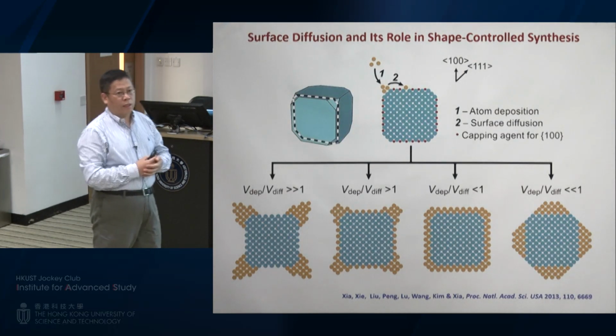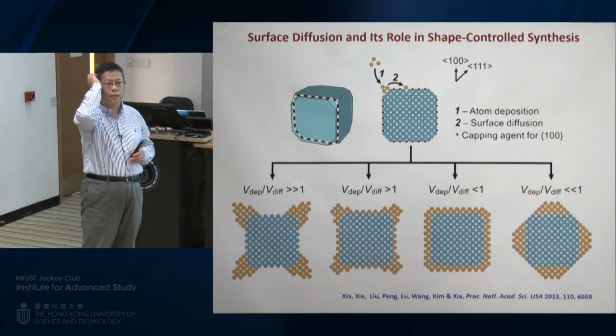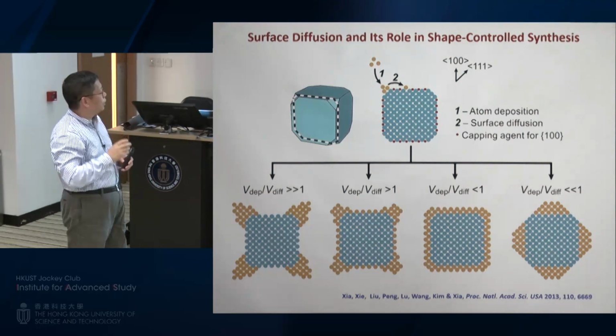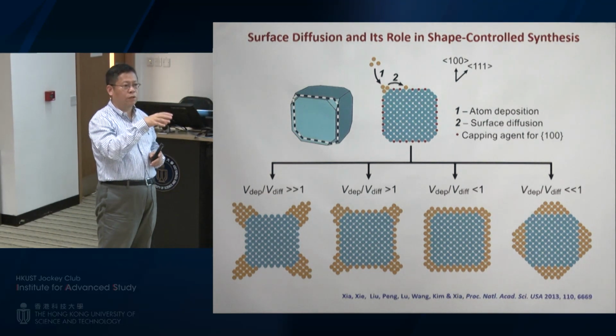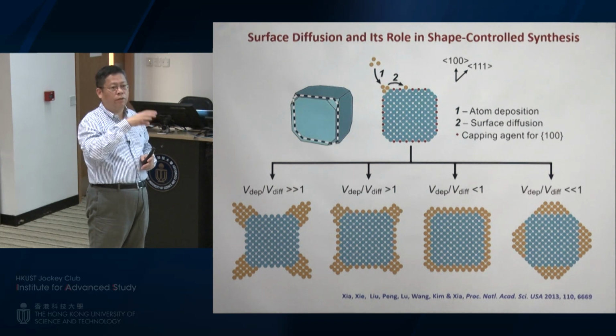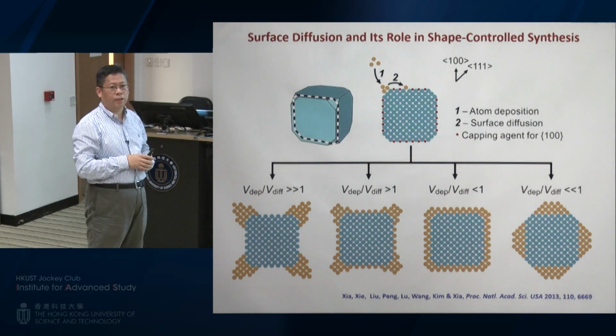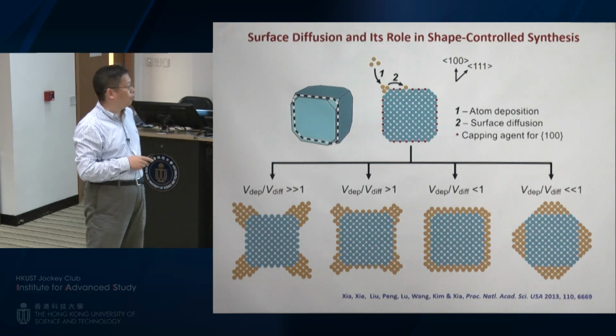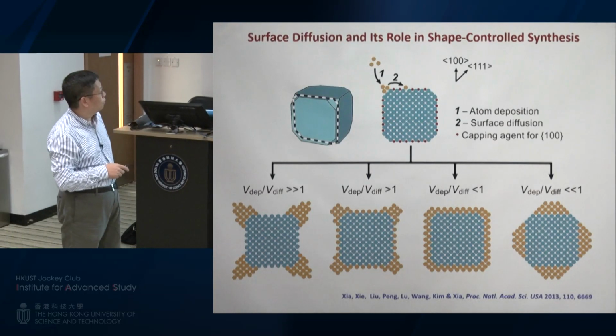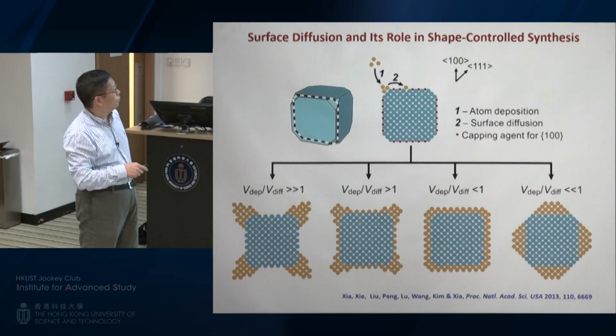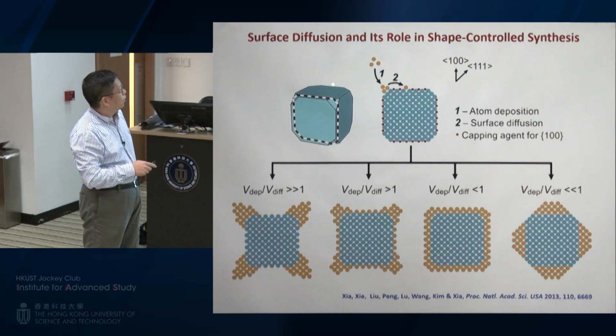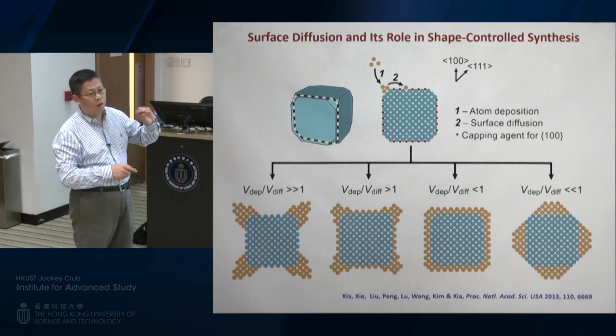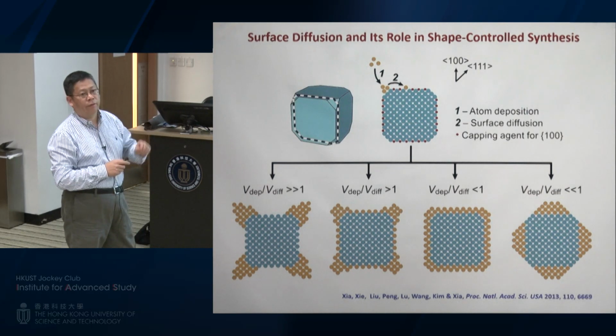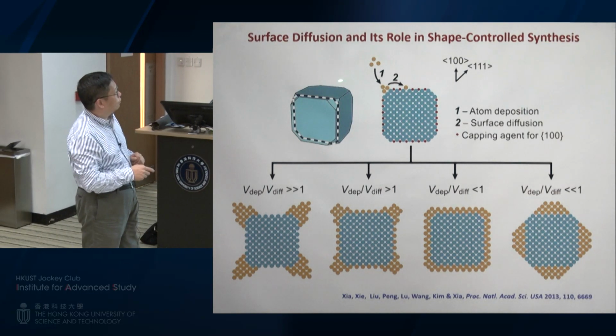And during the growth process, it turned out to be also important for the kinetics, as I briefly mentioned. The kinetics could be understood in this way. Okay, you keep adding atoms to the surface. If the atoms cannot migrate to other areas, they might just pile up at the site of deposition. So eventually, it will change the morphology of the particle. So here's one example based on palladium cubic seed. Palladium cubic seed, you have the side face 100 surface that's capped by bromide ions. That's how we make them into cubic shape. Bromide is a selective capping agent for the 100 facet. But you have corner sites and edges not covered by the capping agent.